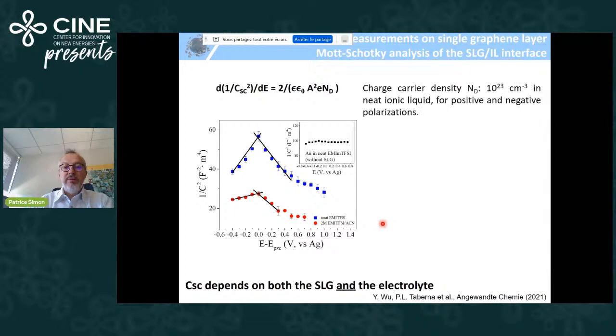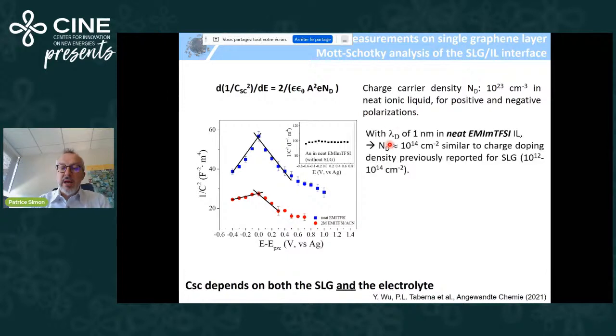And if we go a little bit further, from these slopes we can calculate a charge carrier density of 10 to the power 23 carriers per cubic centimeter in neat ionic liquid, more or less for positive and negative polarization. Which means that if you consider a Debye length of 1 nanometer, which is more or less what we assume for the space charge region when you have big EMI plus ions strongly adsorbed onto it, then you end up with a charge carrier density of 10 to the power 14 per square centimeter, which is really consistent with previous values in the literature.